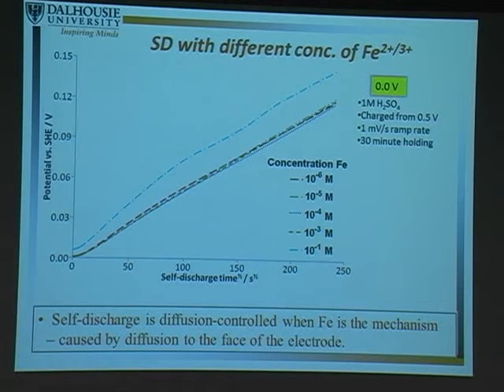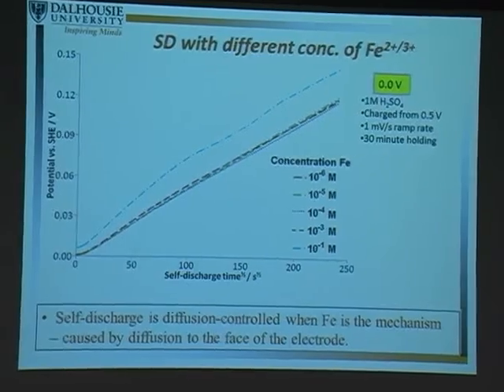So if we go to the negative electrode, what we see is a linear profile when we plot a square root of time. This is telling us it's a diffusion control process. But in fact, until we go to very, very high concentrations for the iron, it's not iron. So whatever's happening in this system, iron can discharge the positive electrode, but does not discharge the negative electrode. Something else is happening here. And so we did a bunch of work looking at electrolyte decomposition. We showed that it's not the electrolyte decomposing. And then we happened upon oxygen reduction as the actual mechanism that's causing this self-discharge.